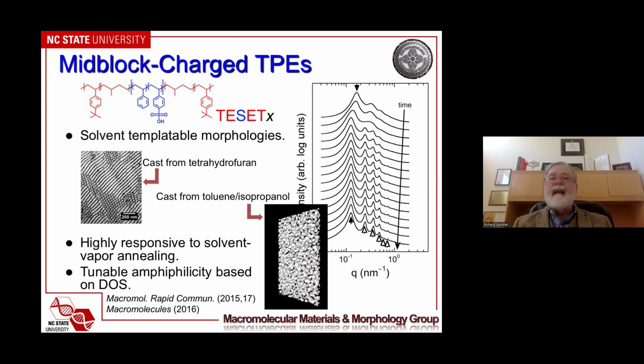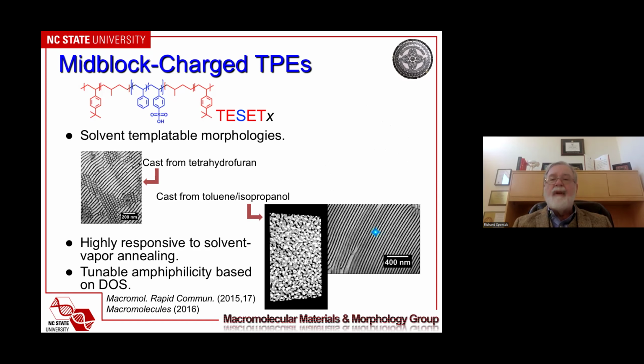And you can see that when we get up here to 6 minutes, the profile has changed rather abruptly and remains the same throughout the rest of the experiment, with those peaks becoming sharper and more numerous, and finally ending at the end of the experiment with 6 orders of reflections. This is a highly, highly ordered material. And if we analyze those profiles, or alternatively look at transmission electron microscopy once again, we see that this is what we produce. So this morphology changes to this within minutes, just based on solvent vapor annealing. Okay, so this is going to be initially the prime player in everything that I talk about.